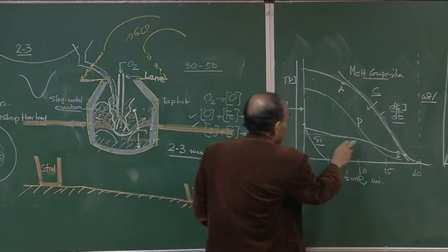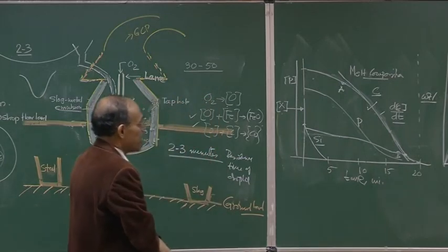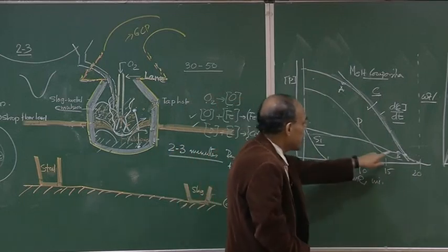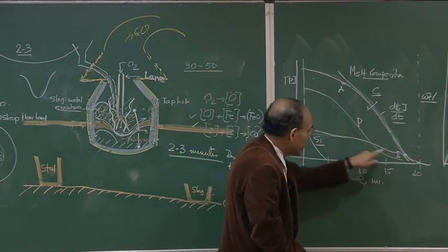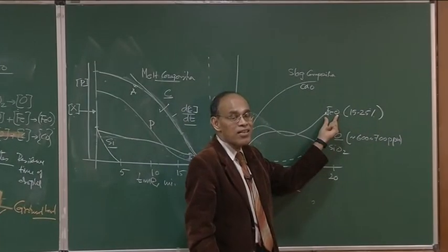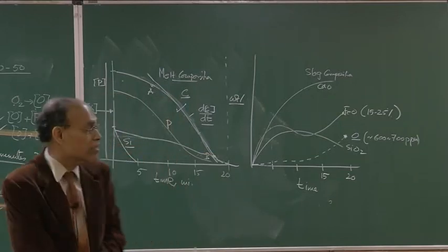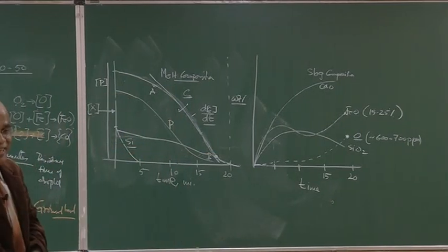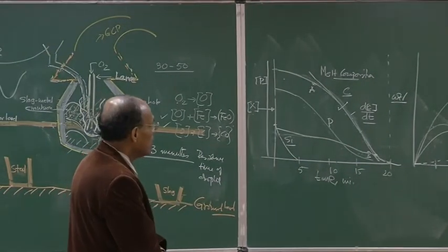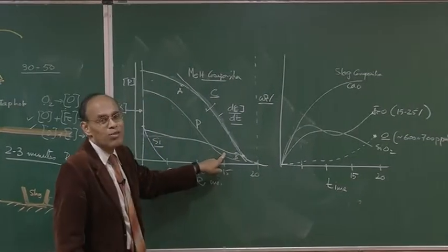In this particular period we have, as we have indicated, a large basicity, but in this case we can get some manganese removal towards the end, because if your oxygen content is large, and as I have indicated when I talked about the manganese reaction, manganese has a somewhat greater affinity towards oxygen. Because the oxidizing potential is very large, some amount of manganese removal is possible.